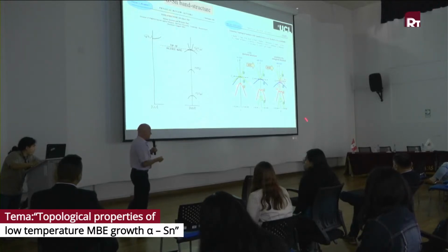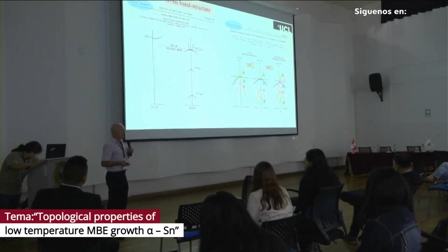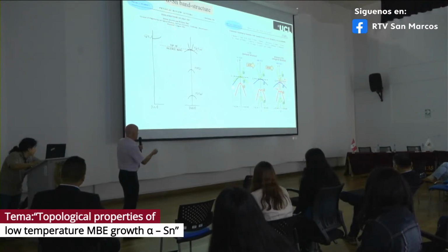all this behavior going on in the band structure is something that we can access with a transport measurement and also with an ARPES measurement. With spin-orbit coupling, it pushes down this spin-orbit split band out of the way here. We have a much simpler band here. And with strain, the strain can open up this band gap.